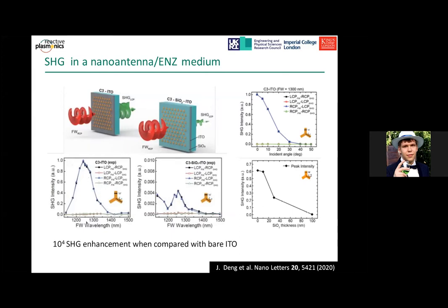And as in the previous slide, we observe 4 orders of magnitude enhancement of the second harmonic as opposed to the bare indium tin oxide. However, I have to say that since the second harmonic generation at normal incidence for bare indium tin oxide is forbidden by symmetry, this enhancement factor is only limited by experimental errors and could in principle be much, much bigger. When we incline the sample a bit, therefore allowing the symmetry non-forbidden components for the second harmonic even for bare ITO, it is important to note that even in this case, the nanostructure enhanced nonlinearity is many orders of magnitude stronger than the bare ITO.